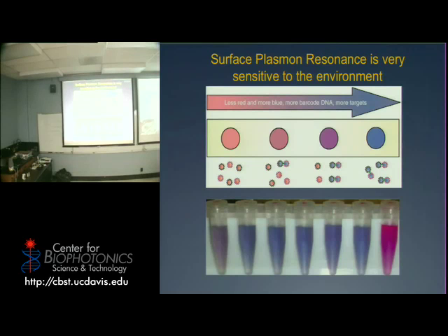As they aggregate, not only do they become larger, but it also perturbs the plasmon resonance. And so they start changing color. It's actually reversed from what is right there, sorry about that, but basically you start from a situation where they're red, kind of like the one you're seeing, and the larger they get, the bluer they get. That's kind of easier to remember, it just goes toward longer wavelengths the larger they get, at the point at which they eventually crash down.